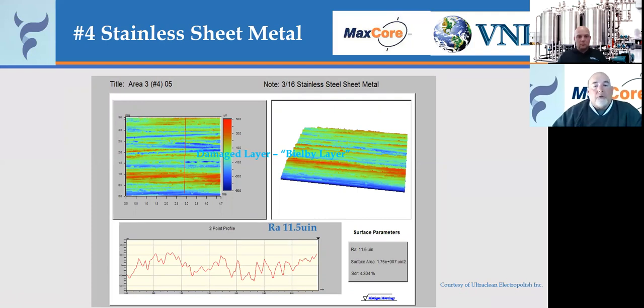So what you're actually doing is removing these peaks from the surface of the steel down to the valleys. So you're basically eating off these high points and removing those down to the low end of the steel. So by doing that, you're not actually reducing the thickness of the material because your thickness of the material is already down at this particular location. All you're doing is smoothing it out.